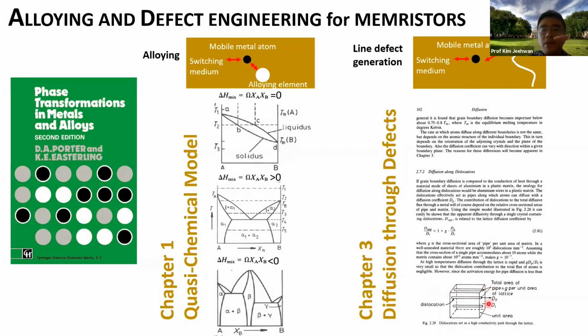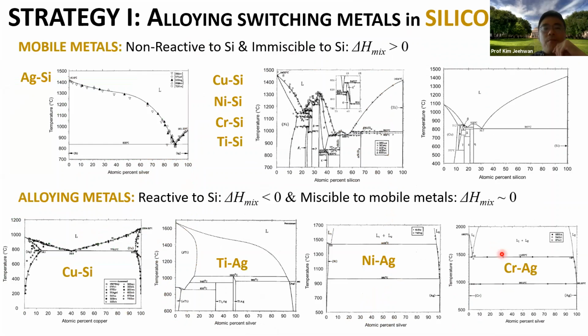So if you can have a single crystalline matrix with this line dislocation, you can confine the ionic movement inside the dislocation. So we apply these two. We were interested in developing these two concepts to have extra control on the synaptic rate in the memristor. Let me first introduce our first strategy, which is alloying the switching metals.